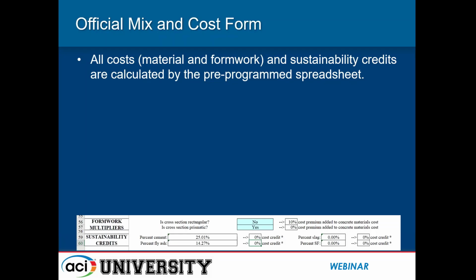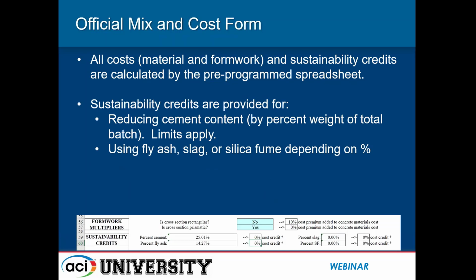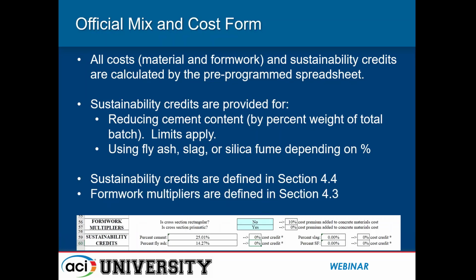So all of the costs and the sustainability credits are calculated by these pre-programmed spreadsheets. The sustainability credits are provided for reducing your cement content. There are limits that apply to this, and also by using fly ash, slag, or silica fume. However, the credits depend upon the percent of fly ash, slag, or silica fume that you have placed in your mix. Sustainability credits are defined in Section 4.4 of the rule sheet, and the formwork multipliers are defined in Section 4.3 of the official rule sheet.